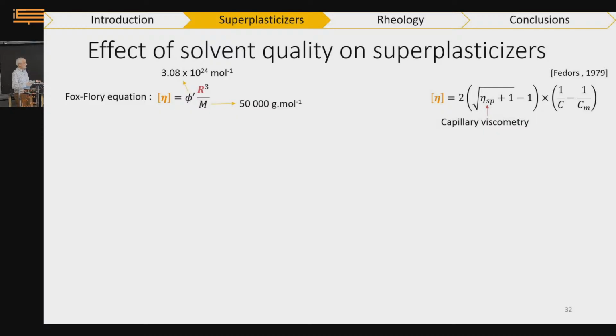So from that, what can we do? As I said, we cannot measure the Flory parameter. What we can measure is the intrinsic viscosity of the solution. Actually, we measure the relative viscosity or the specific viscosity via a capillary viscometer. And doing that at different concentrations of polymers, we can extrapolate to 0.